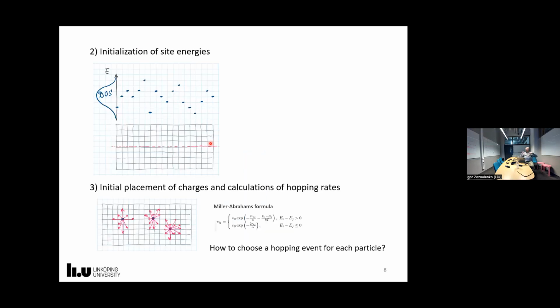Okay, so as we just discussed, this is a disordered lattice. So we start by initializing the site energy. For example, along this line, we consider each of these sites as a possible site for a polaron, and then we introduce some site energy according to the density of states in conducting polymers. Then we have this lattice and we place charges on it according to the charge density that we have in the realistic system. And then we will use the Miller-Abrahams formula to describe these hopping rates.